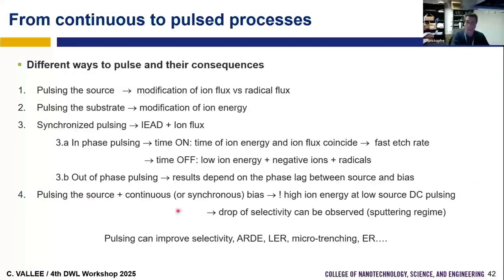So now you have more energetic ions. You may be in the case where you can have very high energetic ions going to your substrate. This can be good, and you can improve your whole plasma process. You can improve etching rate, selectivity, aspect ratio dependent etching, all the different issues you may have, but it can also be bad sometimes.